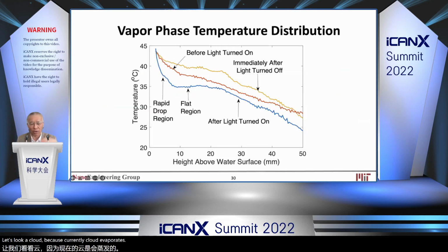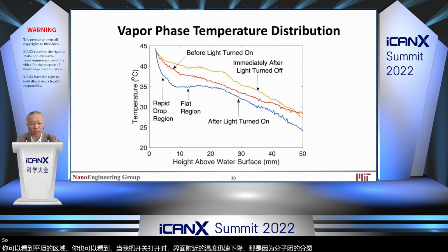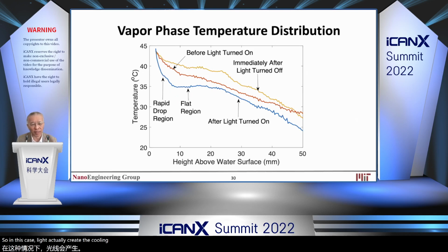And the last experiment I asked Jiandong to do is, okay, this is interesting, and let's try to make it relevant. Let's look at clouds, because currently in cloud evaporation, there's one more picture than before. The temperature also has a flat region, even above water. You can see the flat region. You can also see that when light turns on, the temperature rapidly drops near the interface. That's because the molecular clusters are breaking up. So in this case, light actually creates a cooling, not a heating effect.